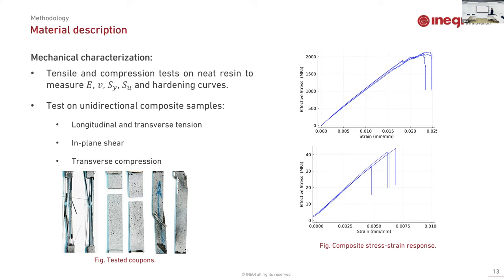Going to the mechanical part, we can do tensile and compression tests on the neat resin and also on the composite using unidirectional coupons: longitudinal and transverse tension, in-plane shear, transverse compression. We measure all the properties that are commonly measured in the material to feed the numerical model if required. We will not spend too much time on that part.